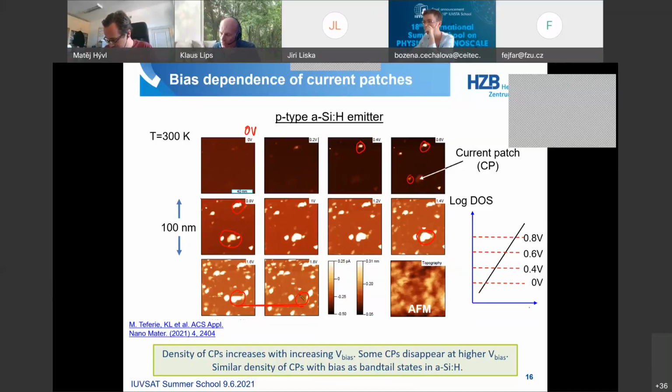And what we find is that it is an exponential density of states, and believe it or not, it matches exactly the density of states that we have for amorphous silicon for hole states. So from this very simple experiment, it seems that we're somehow seeing band-tail states, but that is just due to the fact that they have the same number. This can be a coincidence. So what we actually need is a real proof that these are band-tail states. And I will give you that proof later.